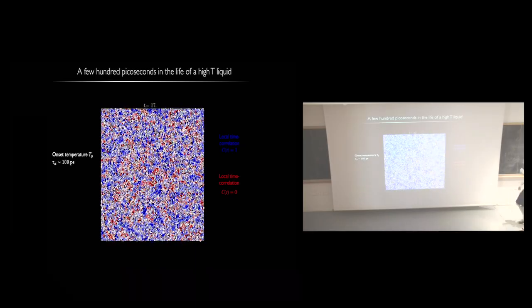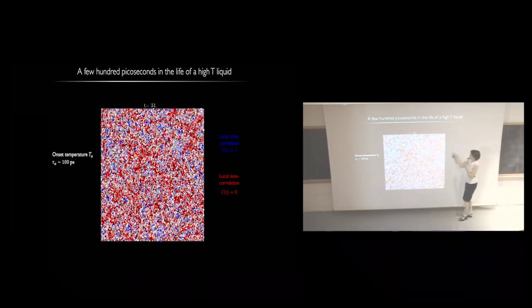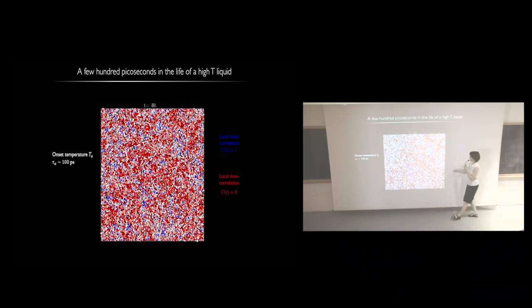So we're looking at the equilibrium dynamics. I showed you already a movie at low temperature, but I still want to show you what happens at high temperature. This is the onset, where the dynamics starts to become super Arrhenius. And again, this is the blue-red picture. Blue regions have the same local structure as time zero, and the reds have a completely different structure.